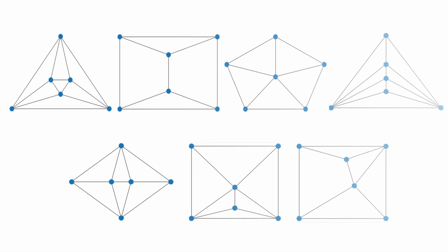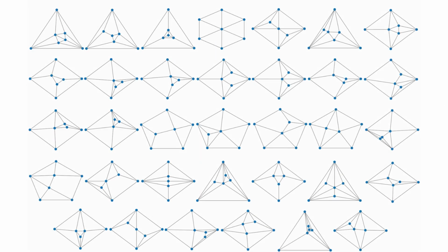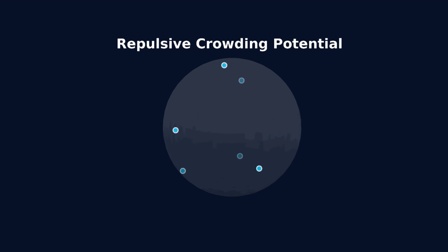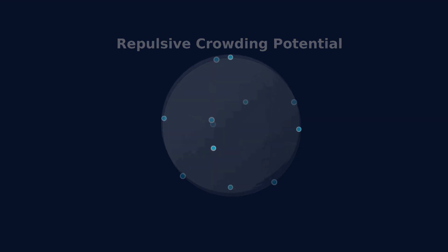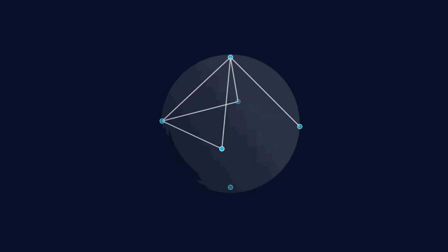For coordination number 6, that gives 7 possible 3-connected planar graphs. For coordination number 7, 34 3-connected planar graphs. We generated them all. Then we embedded each geometry in 3 dimensions and optimized its vertices on a sphere under a repulsive potential, while preserving topology and maximum symmetry.